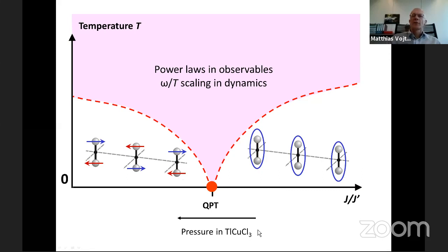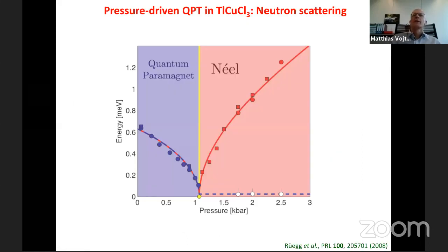And there's one interesting material. Well, there are many actually which realize such quantum dimer systems, but one is thallium copper chloride. And this starts out at ambient conditions on the right-hand side of the phase diagram, but by pressure can be driven through this quantum phase transition to the left-hand side. And this has been studied in quite great detail. And what I show here are results from neutron scattering reported in this 2008 paper. And neutron scattering measures the energy of the magnetic excitations, and that's shown in this plot here.